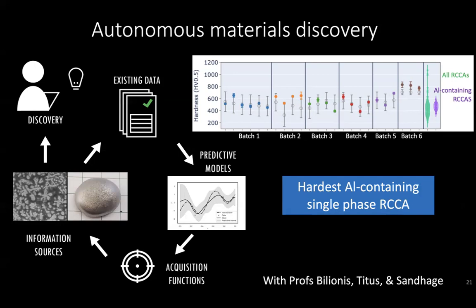Our design space at the beginning, that's also important, was 65,000 alloys. We use CALPHAD calculations, thermodynamic calculations, to narrow that down to 5,000. That was very important. So it's not just AI, domain expertise, what you are learning about material science or chemistry or whatever your field is, is critical. This is not just out of the box and they run. But it really accelerates your decision making, and you're really also delegating the decision making to the machine.